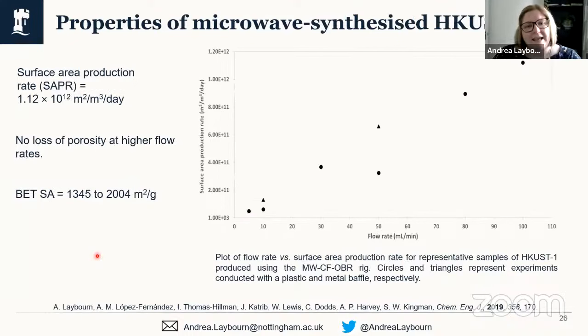Now, as a key point, I've mentioned that we want to maintain the porosity of the materials that we were producing. We wanted to have a look at the effect of this as a function of how fast we were producing it, and therefore the flow rate. And there is a marker that we use called surface area production rate, which is the amount of material based on the footprint of the reactor with the surface area of the material being produced and the time in which the reactor is being operational for. And what we can see is as we increase the flow rate, our surface area production rate, which is on the y-axis, increases as we go up in flow rate.